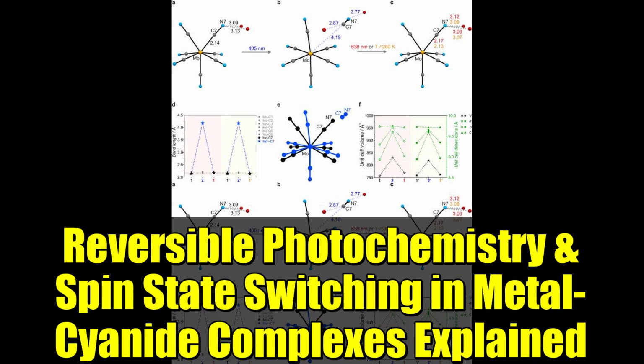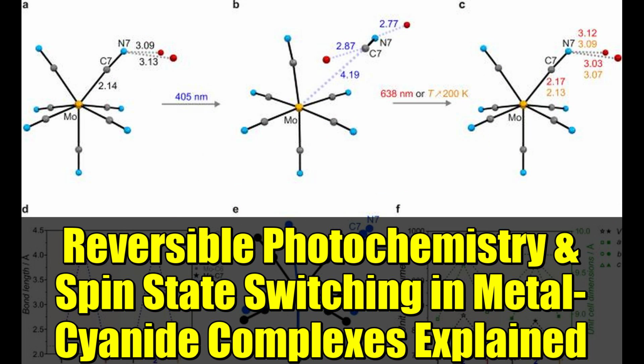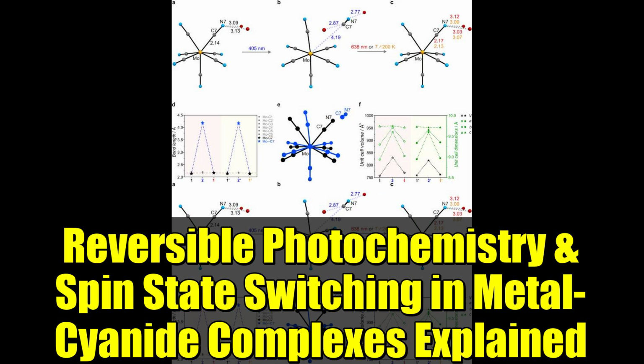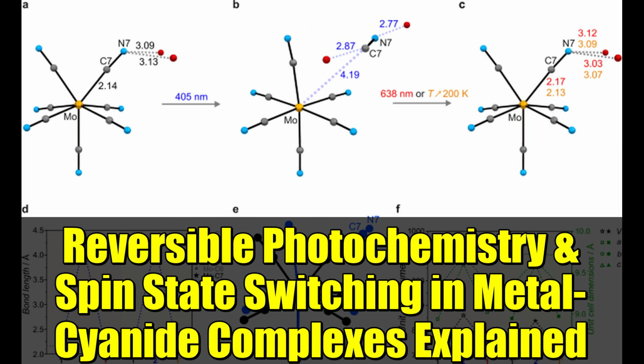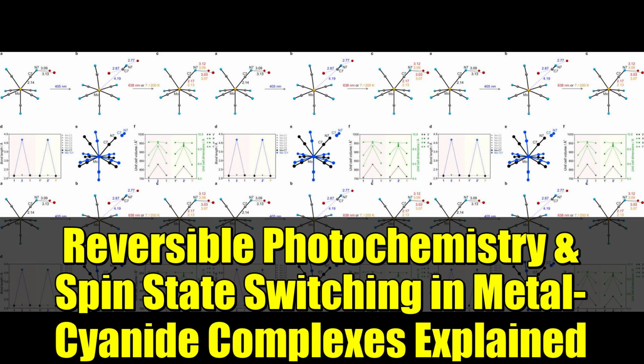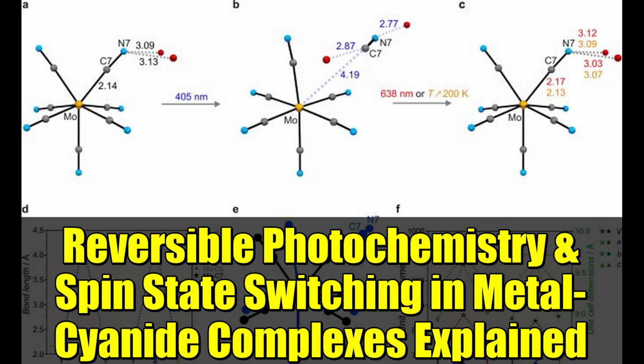Below 3.5 K, these couplings led to an antiferromagnetically ordered state, as evidenced by the M-H data, and corroborated by low-temperature heat capacity measurements. Photomagnetic experiments conducted on 1 at 10 K showed an increase in χT from 0.30 to 1.79 cm³·K/mol upon 405 nanometer irradiation, converting 1 into 2.